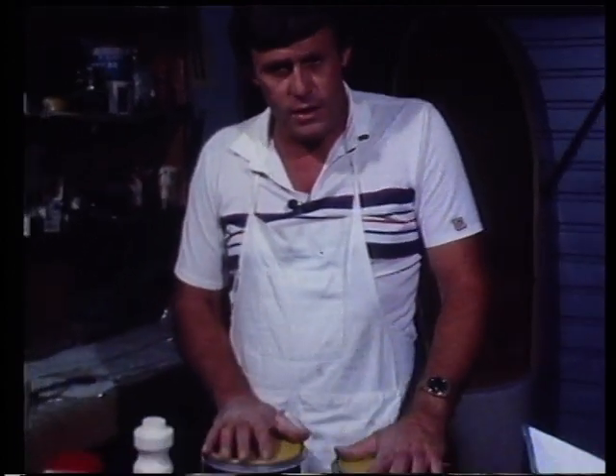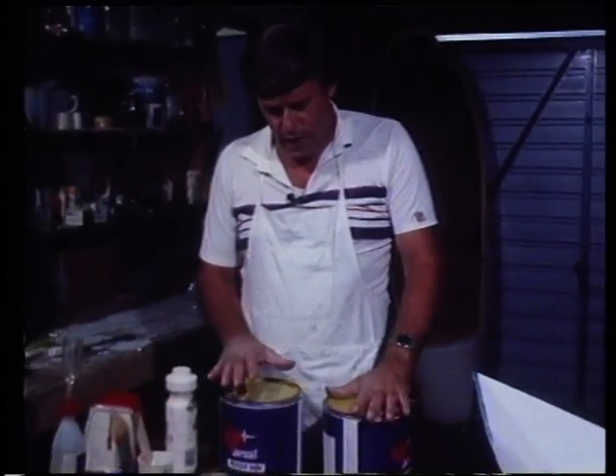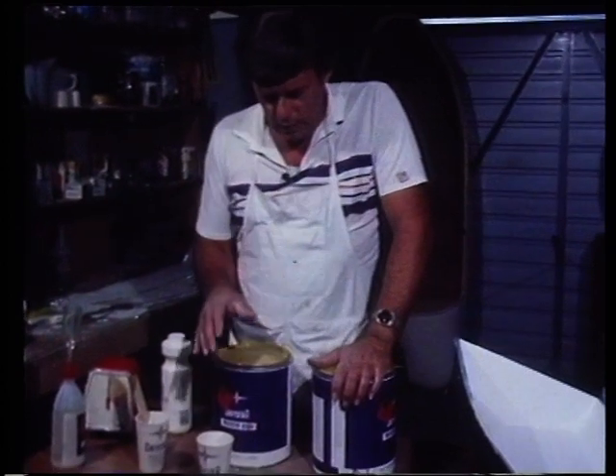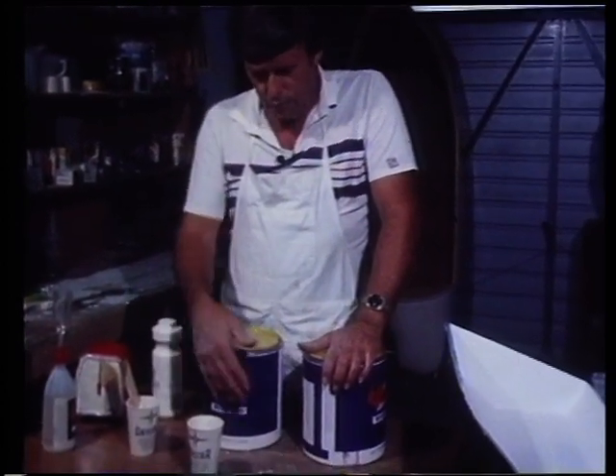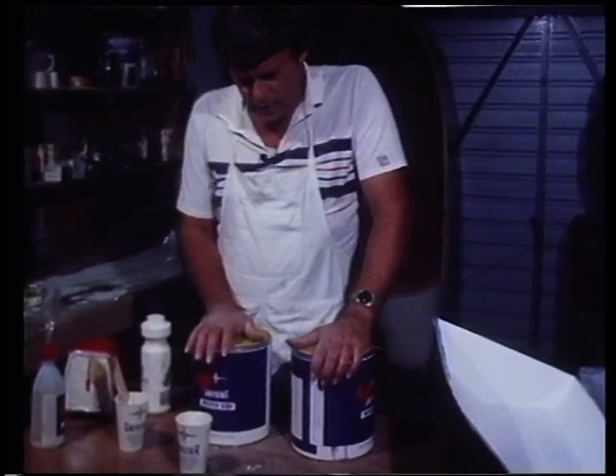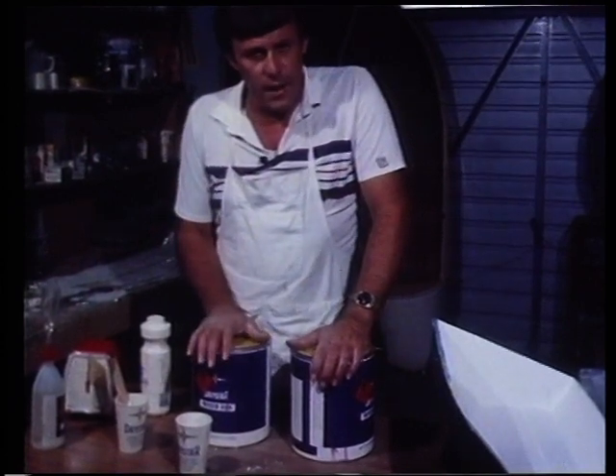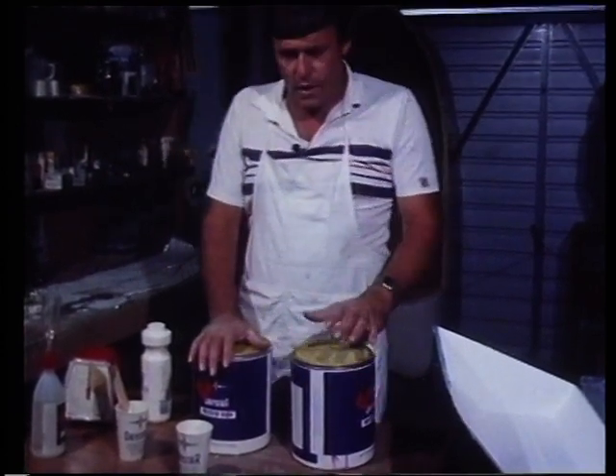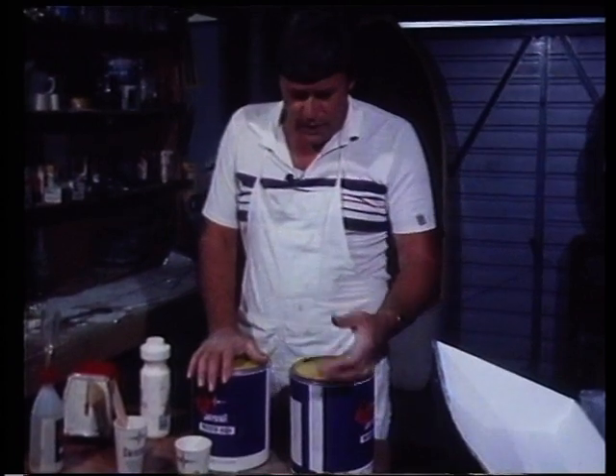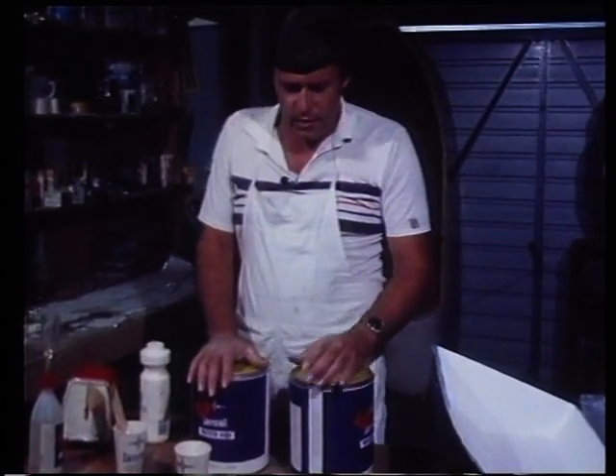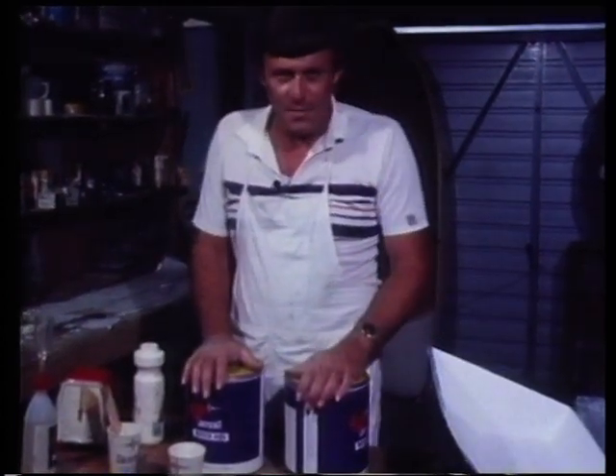So one of the other reasons for keeping it capped and for being very careful with naked flame around the workshop is to minimise the chance of explosion or fire. Now a bit of caution will eliminate any problems. In fact, I worked in this material for over 20 years in Sydney and didn't even ever look like having a problem with fire. So it's not necessarily dangerous unless you are careless and you mistreat it. Now let's get busy and lay the hull up.